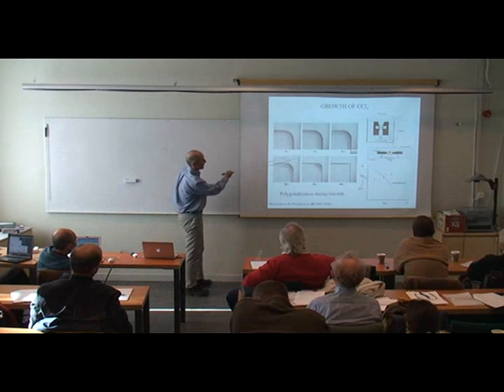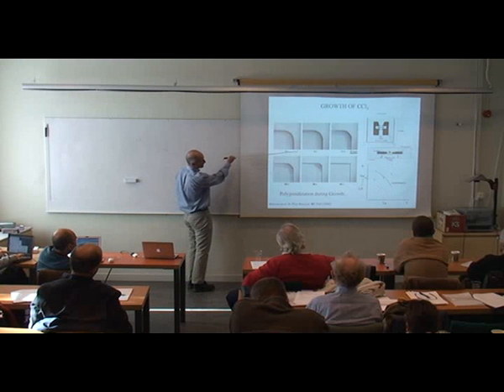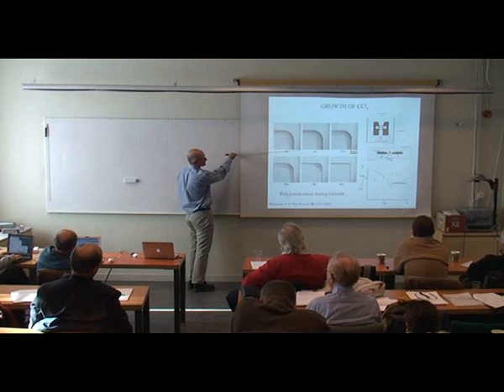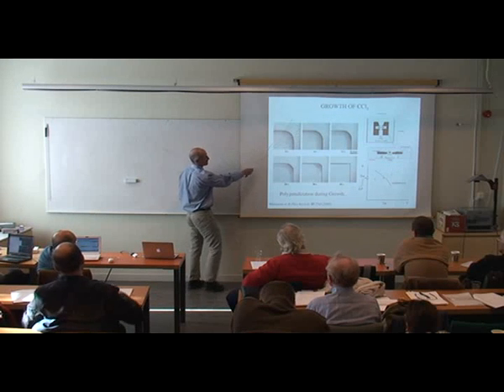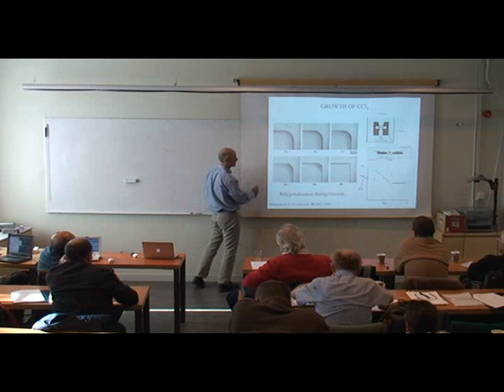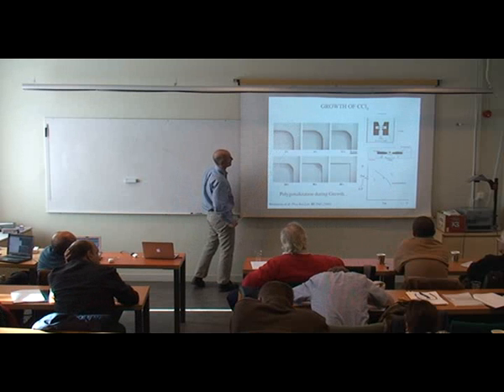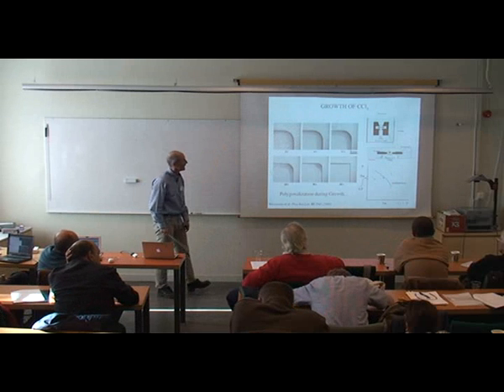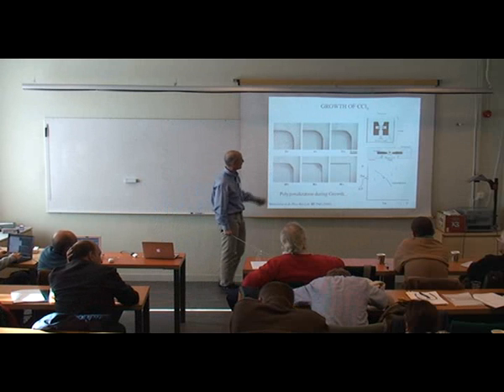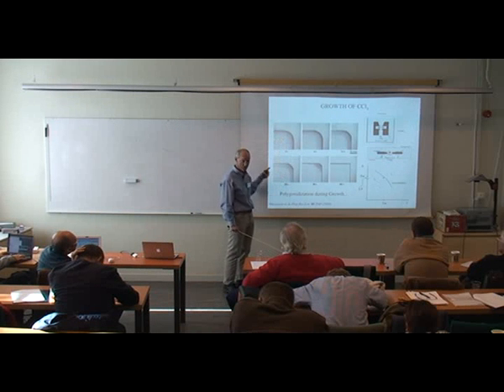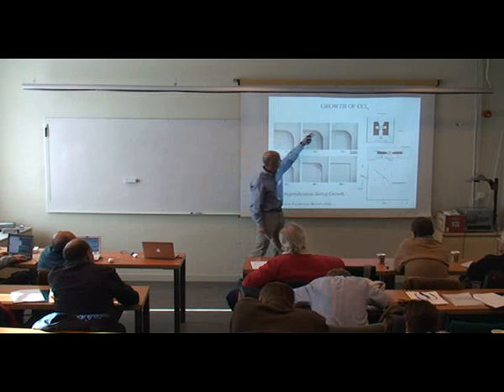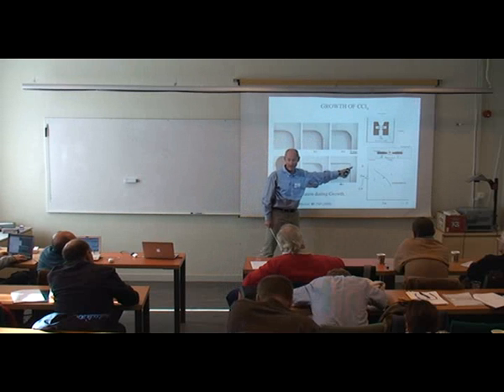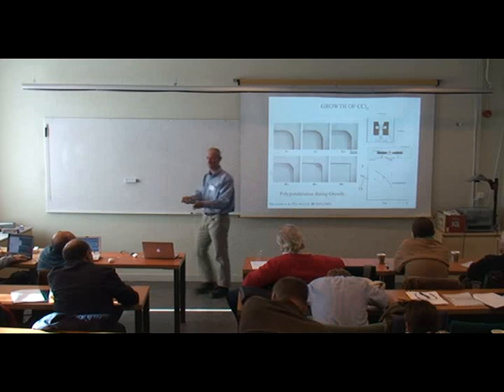Here's an experiment of an axisymmetric, nearly two-dimensional system of CCl4 growing from its melt phase. And this is just the upper right-hand quadrant. You have, say, all orientations on the surface between 0 and pi over 2. So it's a continuous surface curvature there. And you grow it. And what you see, of course, is that these hardly move because there's activated growth parallel to the facets. And the rough orientations grow out of existence, okay, leaving the system fully faceted.